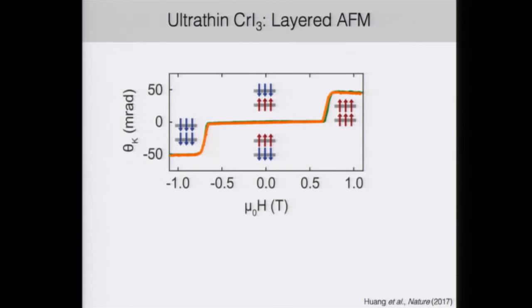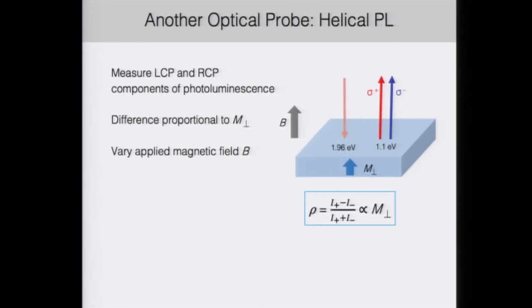So we can understand it as undergoing this switch once we apply a large enough field to polarize both layers with the applied field direction. So we then turn to another optical probe to further study chromium iodide. In a similar setup, again with Xiaodong Xu's group at the University of Washington, we can use helical photoluminescence to read out the magnetic signal as well.